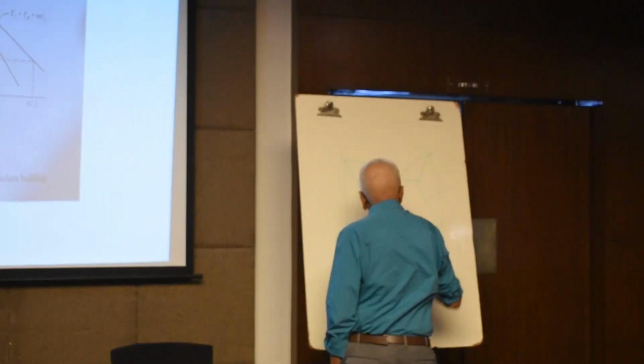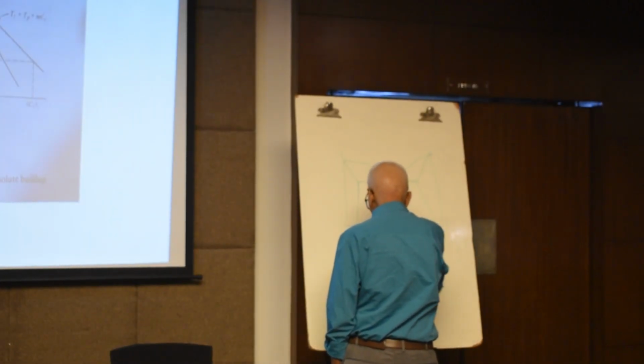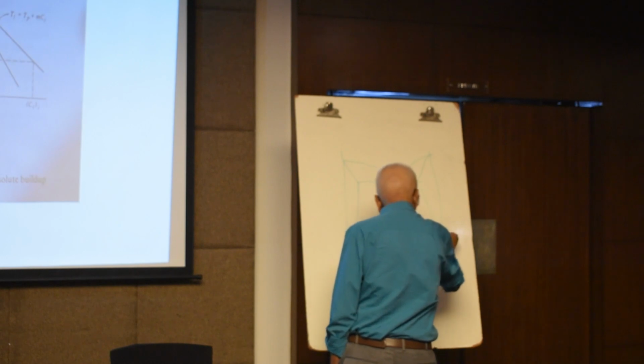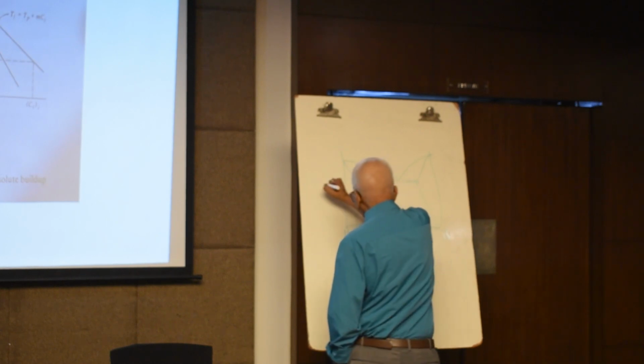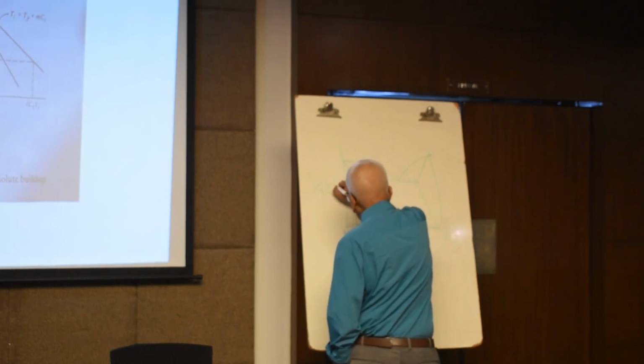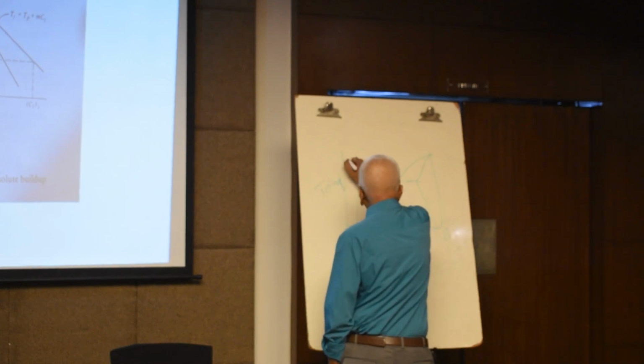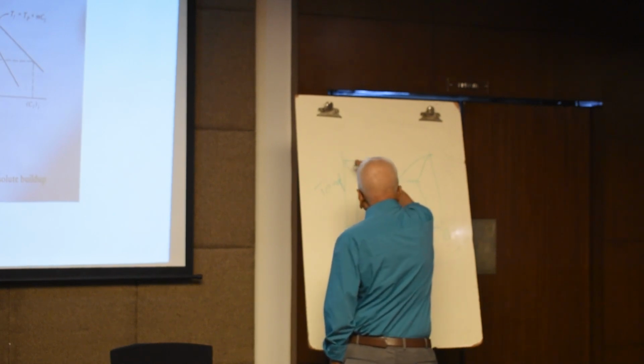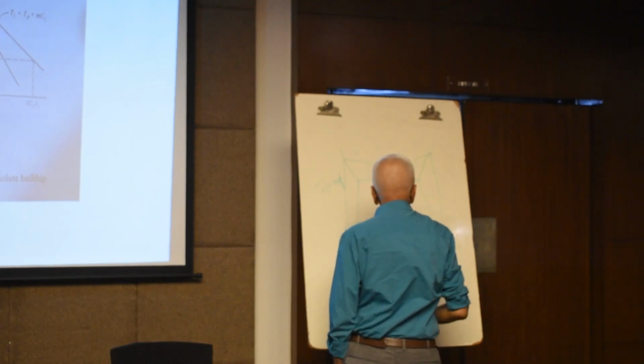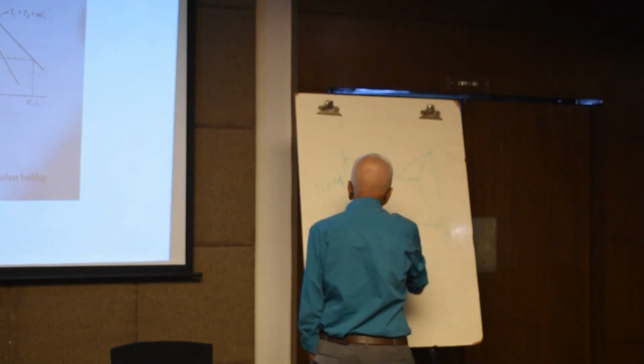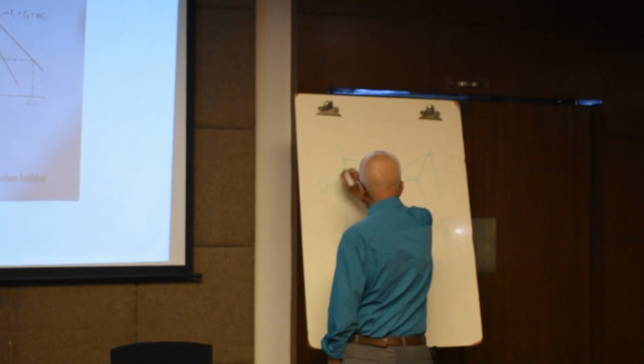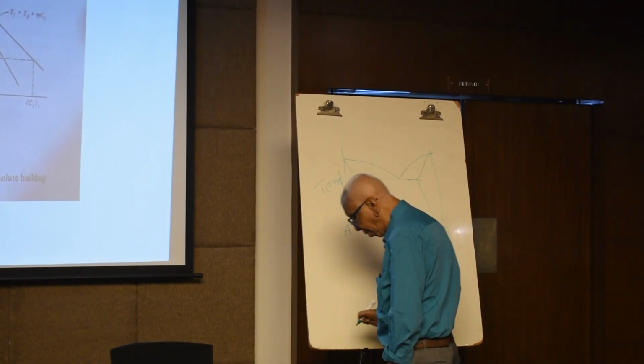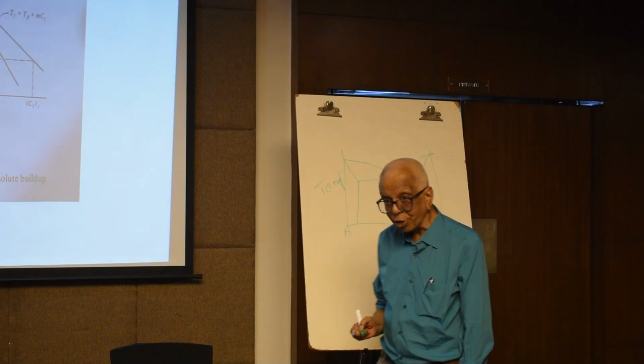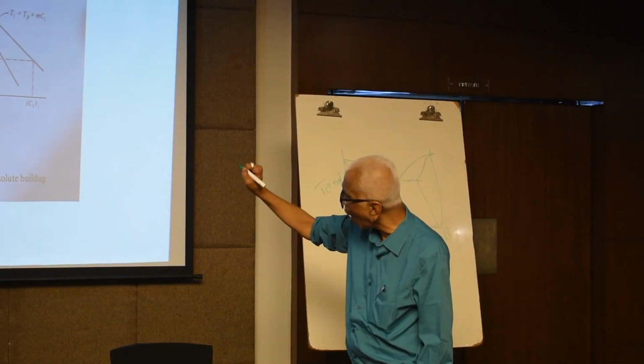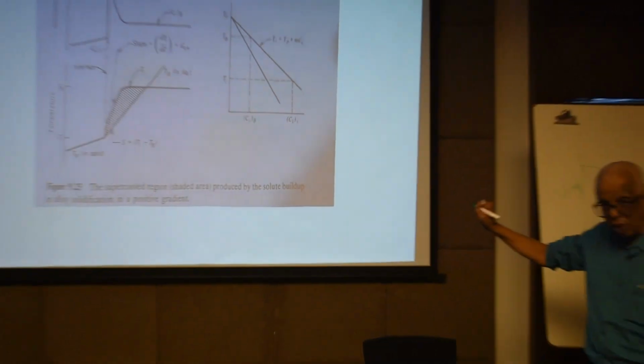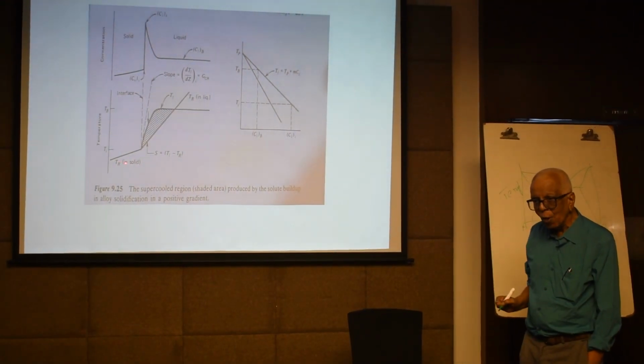And this is the eutectic phase diagram, AB, and the y-axis is temperature. This is a liquidus curve. This is a solidus. This is a solidus. So if you have a liquidus, that gradient is this liquidus temperature gradient. And now if the thermal gradient is below that, then that is what is known as supercooling.